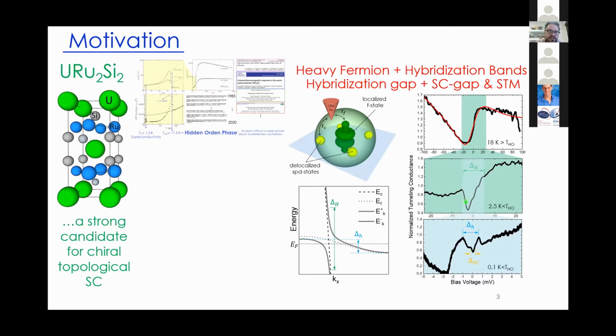But decreasing in temperature and in energy inside of this Fano structure, we can see evidence of the hybridization process. In the case of uranium-ruthenium-2 silicon-2, these features that we can see in these peaks have been linked to the hidden order phase. And also, if we decrease the temperature below the critical temperature and also the energy, we can see evidence of the superconducting gap at very low energies.